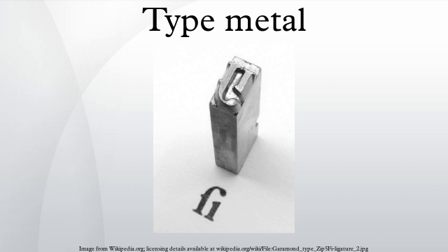The same applies to aluminium, although this metal will float on top of the melt, and will be easily discovered and removed, before it is dissolved into the lead. Magnesium. Magnesium plates are very dangerous in molten lead, because this metal can easily burn and will ignite in this way the metal in the pot. Iron. Iron is hardly dissolved into type metal, although the molten metal is always in contact with the cast iron surface of the melting pot.